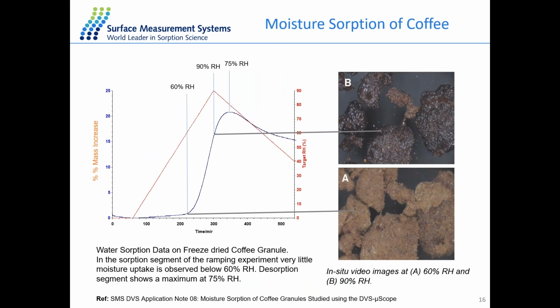A case study related to the ramping method here is about the coffee granule, where we used the ramping method on the coffee granule, exposing it to humidity from 0 to 90% RH and then desorption back to 40% RH. So during the sorption process up to 60% RH, the sample didn't pick up lots of moisture. It's quite stable before 60% RH. But after 60% RH, there is a dramatic increase in the mass change. And for the sample image taken at the end of 90% RH, you can see a clear transformation or color change for the sample compared to 60% RH.